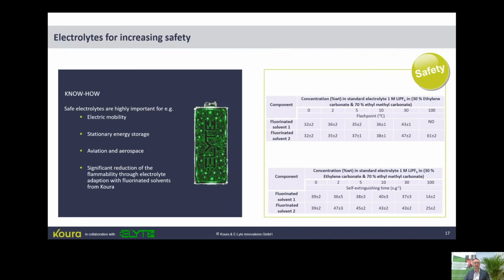Okay, coming now to the first results I would like to show you. The influence of fluorination on safety, and therefore I want to show you on the right-hand side a table containing flashpoint values, and the lower one containing self-extinguishing time values. Of course the first one you would like to increase, so you can dramatically increase the flash point by using fluorinated solvents. And of course, you can decrease the self-extinguishing time also by fluorinated solvents. So this is actually well known. However, it is important that these molecules also act in a good way together with the other electrolyte ingredients. And there, of course, we can see a significant reduction, and this for sure means an increase in safety.